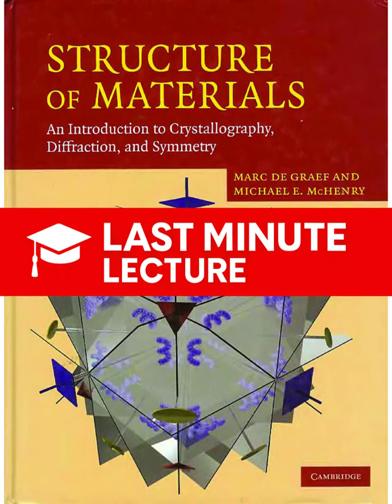And beyond these perfect crystals, you can also get amorphous or non-crystalline forms of ice. You can. We can create low-density amorphous ice, LDA, and high-density amorphous ice, HDA. And the difference in density is striking. What are we talking about? LDA is about 0.94 grams per cubic centimeter at atmospheric pressure. But if you compress normal hexagonal ice at a very low temperature, around 77 Kelvin, you can achieve HDA with a density of about 1.17. Wow, that's a huge difference. You're getting structurally distinct versions of the same molecule just by playing with pressure and temperature.